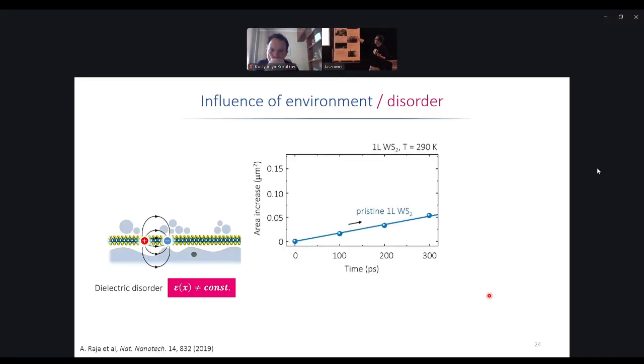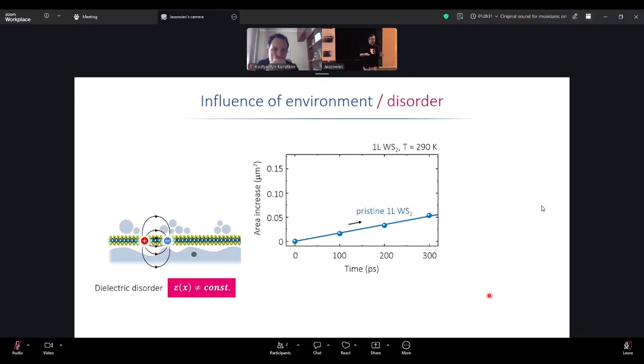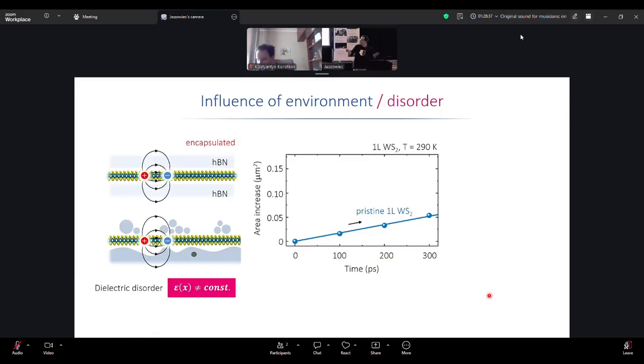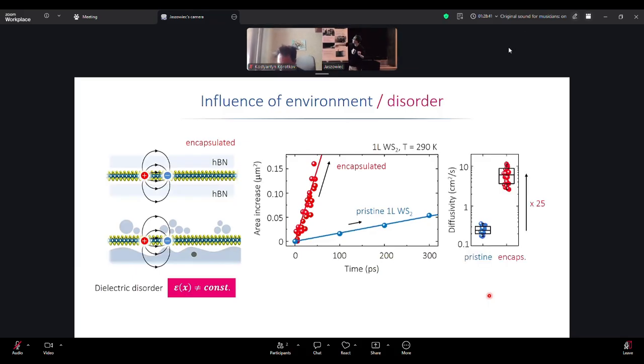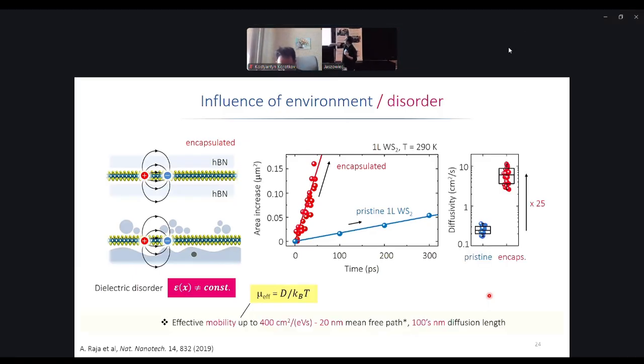So in this case, the transport is relatively slow. But if one makes sure that the dielectric environment is constant, the band gap is flat, the exciton binding energy doesn't change, and the transport becomes very fast. The change is almost a factor of 30. And now we can talk a little bit about the numbers. So this diffusivity at room temperature can always be converted into effective mobility. This is the so-called Einstein relation. There are certain limits where it should not be used, but in many, many cases this is applicable.